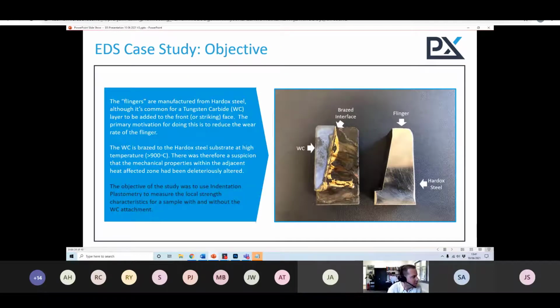So if we look at those flingers in slightly more detail, there's two examples in this particular image, and they're manufactured from Hardox stainless steel. On the right hand side, you've got Hardox stainless steel in its as received condition, which is fine, but on the left hand side you've got one of those components which has had a tungsten carbide insert brazed to its front surface, and of course that is designed to help prolong the wear life of the components.